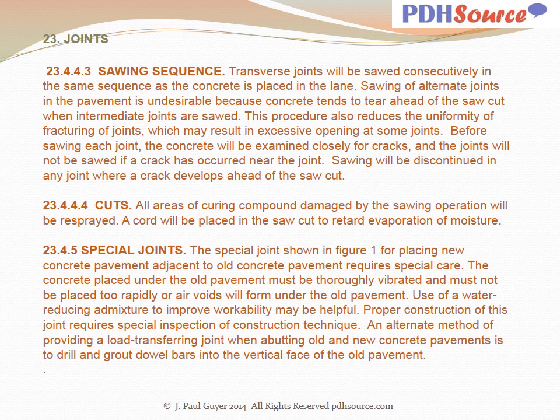The sequence of sawing: transverse joints will be sawed consecutively in the same sequence as the concrete is placed in the lane. Sawing of alternate joints in the pavement is undesirable because concrete tends to tear away ahead of the saw cut when intermediate joints are sawed. This procedure also reduces the uniformity of fracturing of joints, which may result in excessive opening at some joints.